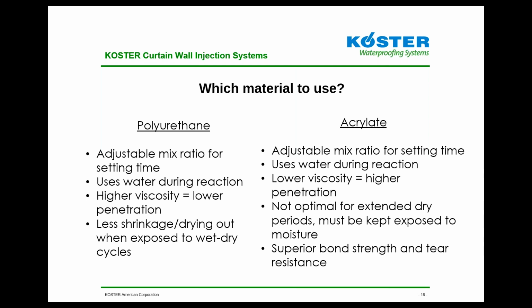The main difference between the cured products is the requirement of a moisture source for acrylate products. If left to dry completely, these products may become rigid and shrink slightly, increasing the potential for an effect on the performance of the cured product. Now, this isn't something that just happens overnight or instantly. Normally, a completely dry period of greater than 3 months is required to cause material to dry out and shrink. When these products are re-exposed to water, acrylates will return to their original form and shape and become more gel-like instead of remaining as rigid as they are when they completely dry out. All the material needs is ground moisture to remain elastic and flexible.